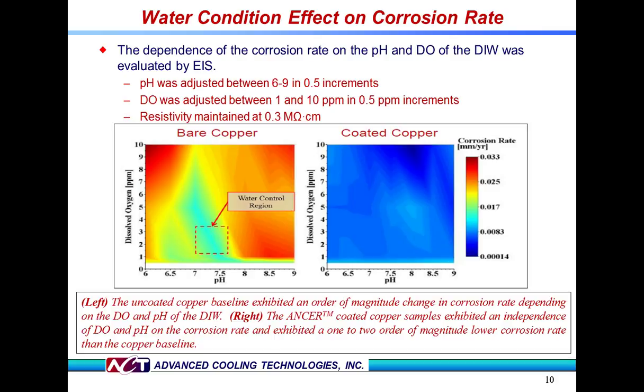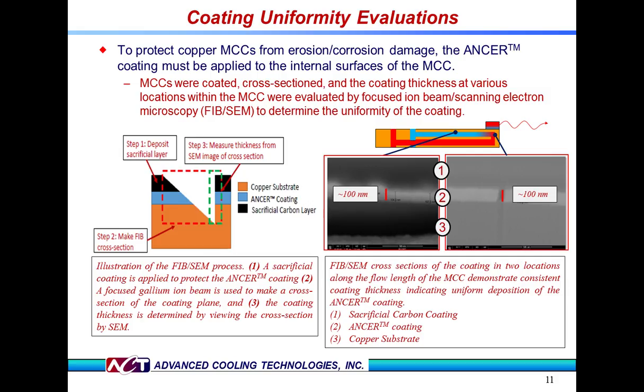The ANCER-coated samples on the right showed essentially no variation across both test parameters, indicating that with ANCER-coated microchannel coolers, both dissolved oxygen and pH requirements can be relaxed without any negative consequences in erosion-corrosion protection. This offers the potential to save money in both equipment and operational costs.